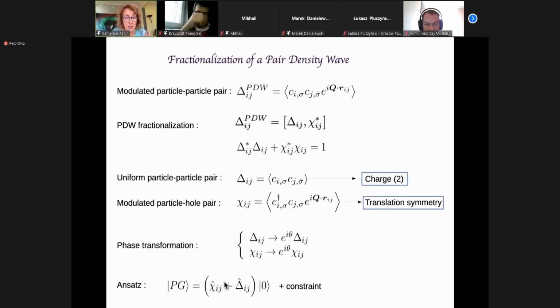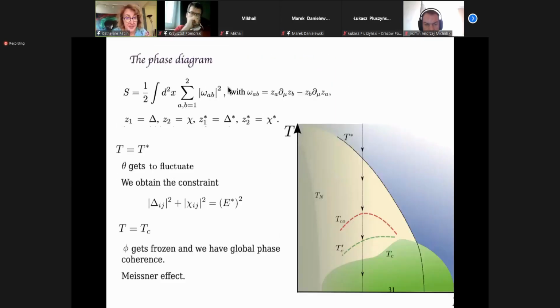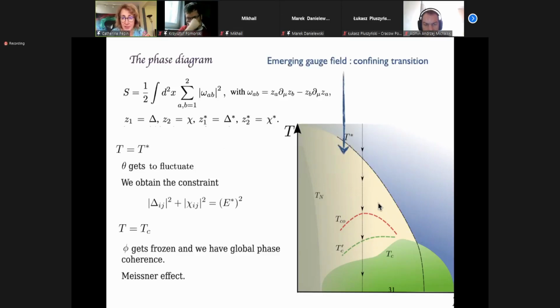The assumption we made is that charge is not an epiphenomenon. To be meaningfully entangled with the superconductivity, it has to be of the same order of magnitude. So again, like for the SU(2) emergent idea, here the effective field theory is a chiral rotor, so it's basically non-linear. You can show, for example in old papers by Perelomov, that this is equivalent to a CP1 model. So basically it's a non-linear sigma model plus gauge fields, these famous emergent gauge fields. And here we have an emergent gauge field with a confining transition. So confining, deconfining, this is the pseudogap.